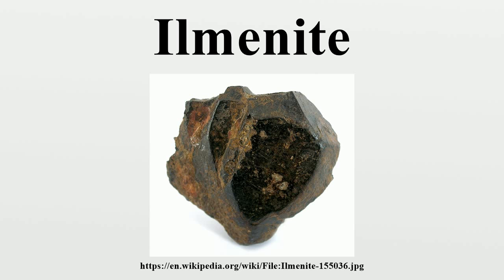In some highly differentiated felsic rocks, ilmenites may contain significant amounts of pyrophanite molecules. At higher temperatures it has been demonstrated there is a complete solid solution between ilmenite and hematite. There is a miscibility gap at lower temperatures, resulting in a coexistence of these two minerals in rocks but no solid solution. This coexistence may result in exsolution lamellae in cooled ilmenites with more iron in the system than can be homogeneously accommodated in the crystal lattice. Altered ilmenite forms the mineral leucoxene, an important source of titanium in heavy mineral sands deposits.